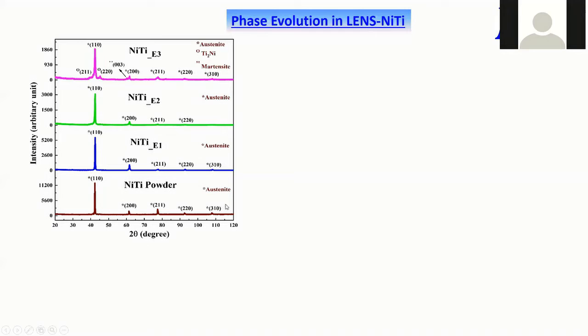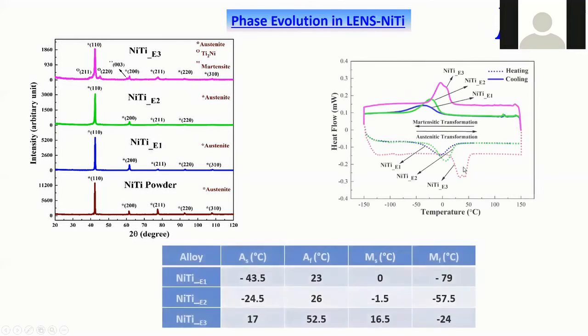Okay, these are the XRD patterns for all these, and we can see that we started with the same powder in all three cases, whereas we end up having different phases if we are varying the laser energy densities. Okay, same goes for the DSC thermogram once again. So the scanning calorimetry actually shows that there is a variation in the austenite and martensite start and finish temperatures if we simply vary the energy density.